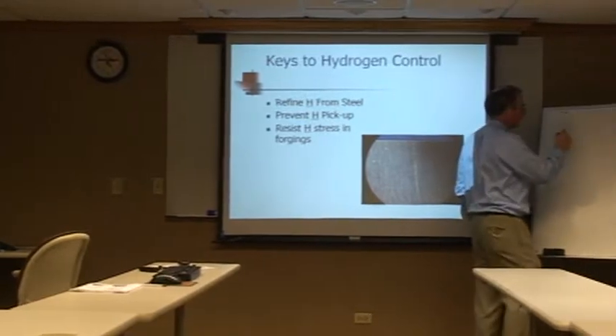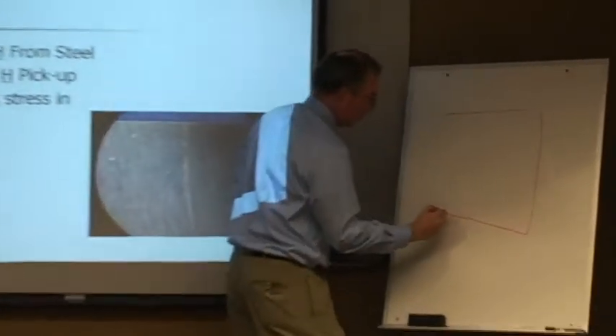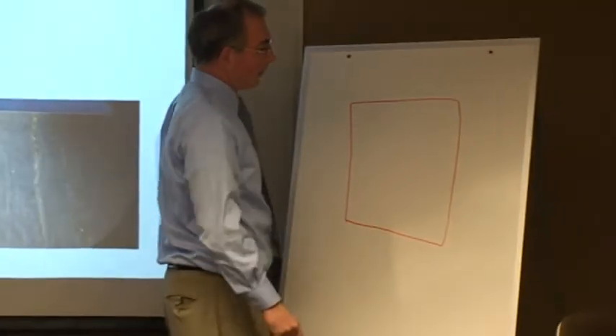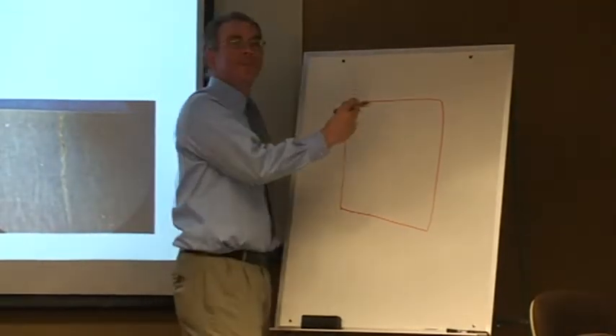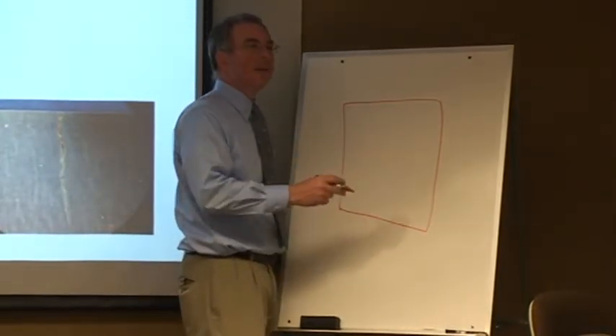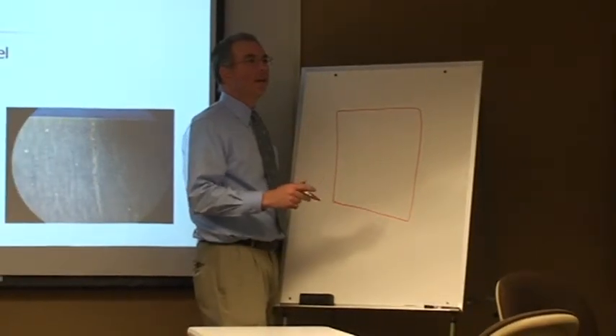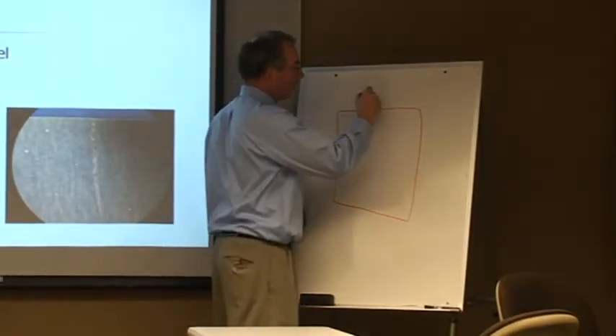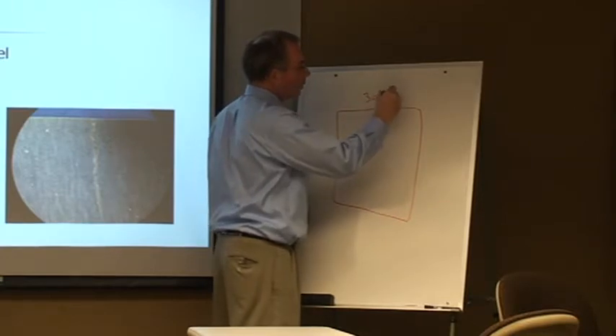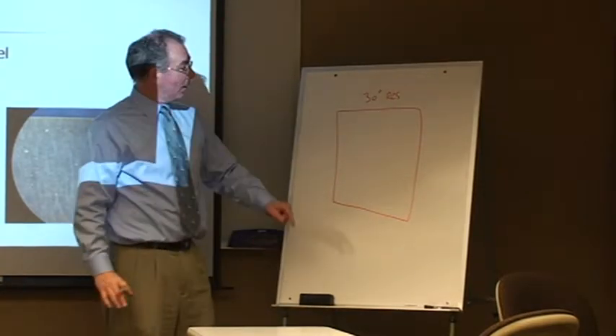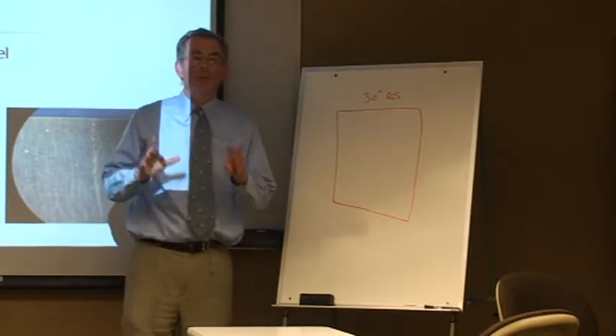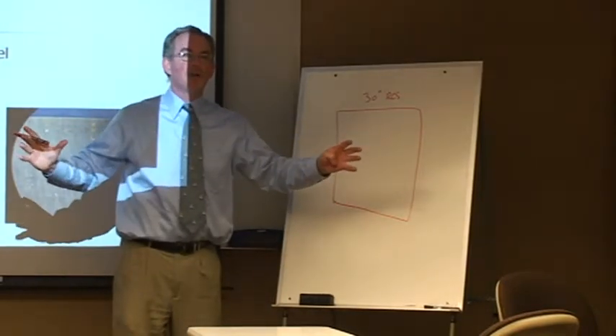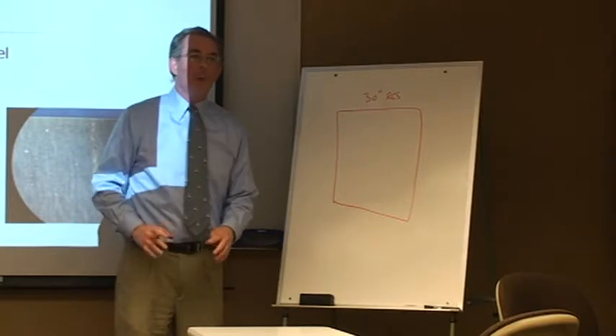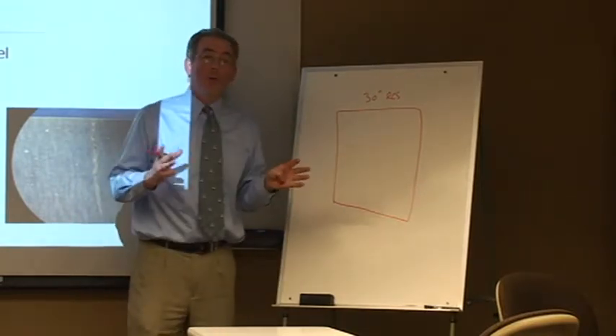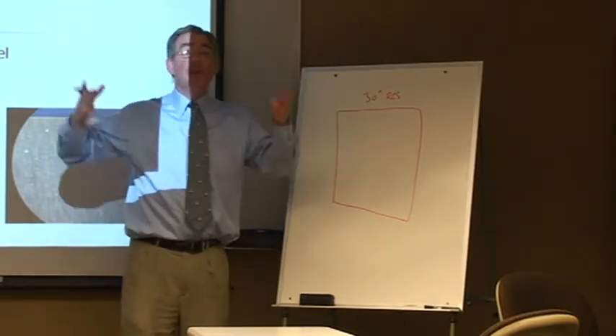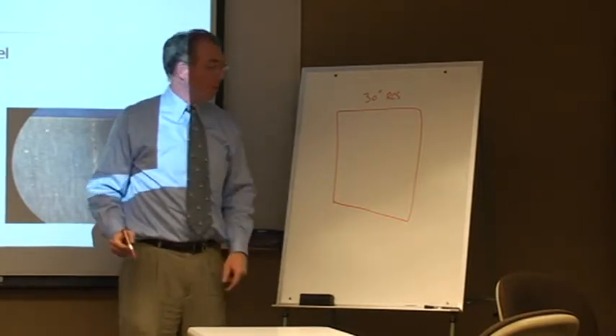is if you make a cross section, and this is a forged, I don't know, what size, Chris? What do we make this? Well, let's say 30 inches. All right, so this is a 30-inch round-cornered square, which was forged. Number one, we have to make sure as a steel maker that the overall bulk hydrogen content of this steel is as low as possible, especially with the larger ingot size, typically the larger cross-section that's going to be made.